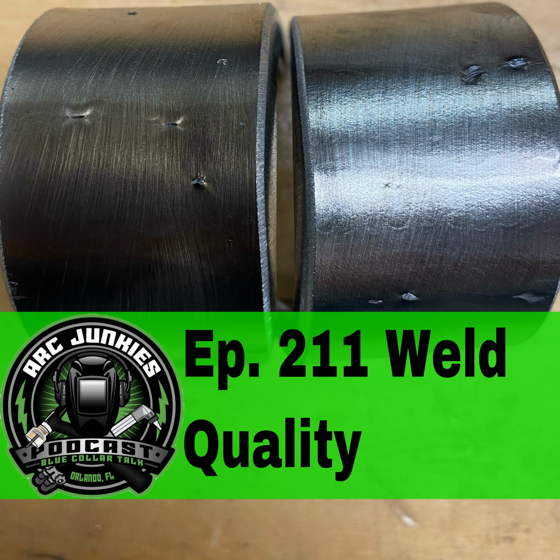So if you have run-on tabs or run-off tabs, or wherever you're starting and terminating your welds, make sure that you clean the slag from those areas, because your weld pool can in fact pull that stuff in with it. And now you have it in your welding zone. And like I said, once you start cutting this stuff apart or doing different non-destructive testing, it's going to rear its ugly head and you're going to see it again. So don't rely on turning it up 10 amps and burning it out, because like I said, you're just covering it up. So try to avoid that.